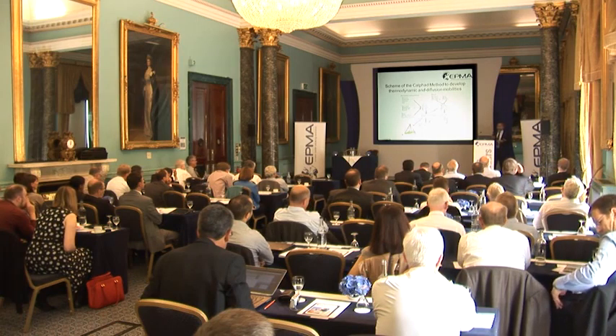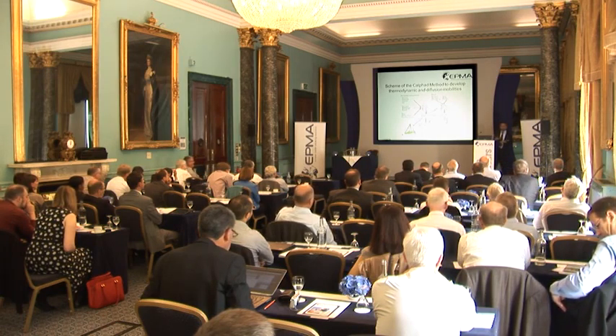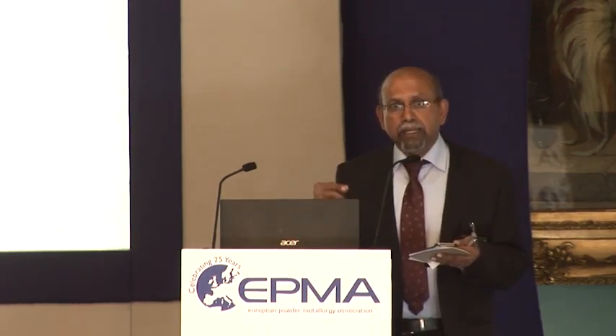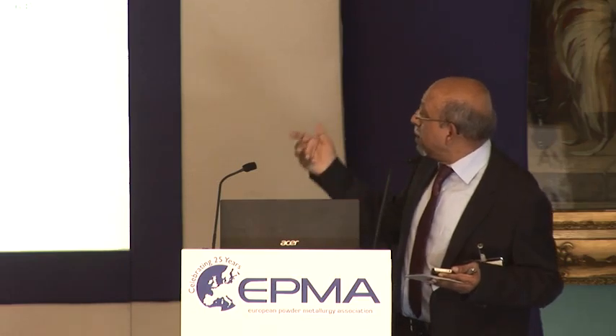Today, Suzanne Norgren said she can make it in 10 minutes. So it's not only about phase diagrams, it's about diffusion and kinetics as well. We are progressing along this, but to have good phase diagrams calculated, you need good experimental results. And that is, as usual, always the bottleneck. So this is an example how a calculated phase diagram could look like for tungsten carbide cobalt. I don't have to go into detail.